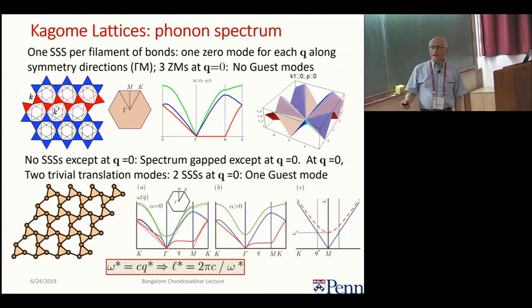Surprisingly, if I just twist the lattice like this, instead of adding next nearest neighbor bonds, I get the same thing, with a gap here that's proportional to the sine of the twist angle that I put in. So now if I look along M to K, then before I've twisted, I have this knife edge coming in, which you see up there. I twist it, and I get this.